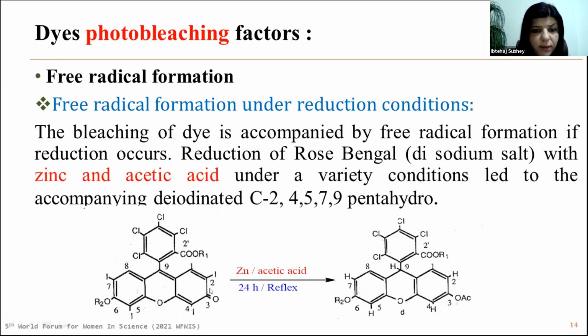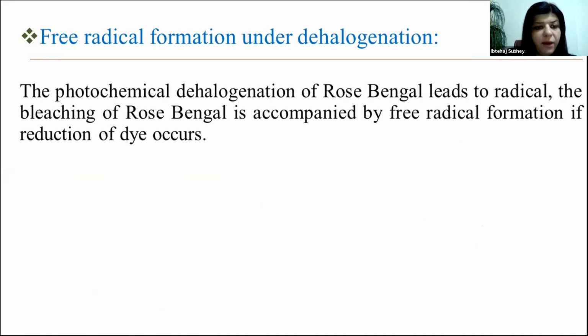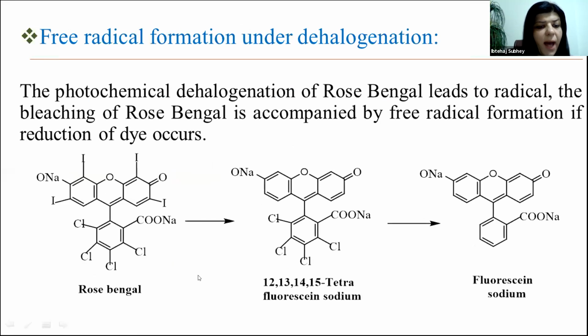We see dehalogenation at positions number 2, 4, 5, 7, and 9, giving a pentahydro product. So according to this reaction, free radical formation and photobleaching appear during the reaction. Free radical formation by dehalogenation is another pathway to forming free radicals. Here, this is the structure of Rose Bengal. In the first step, we see the iodine atoms leaving, and in the second step, the chlorine atom leaving in decolorization. This is fluorescein sodium. According to this reaction, free radical formation and photobleaching appear.